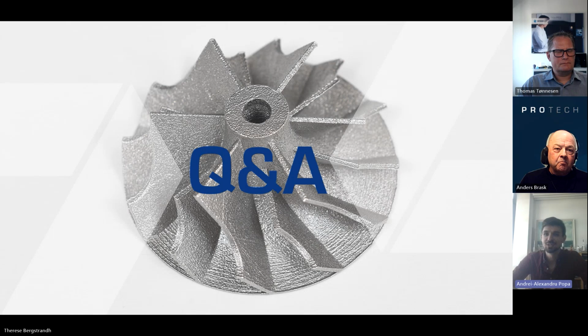Oh no, if you return to this large copper part we made, it consistently had bulges. There were bulges that did not prevent the printing from succeeding in the end, but that's exactly because of the soft recoating. So we could tolerate a little bit more in the geometry. So it's more fault tolerant in that sense. The design with a soft recoater is more tolerant, which means you have a higher chance of actually getting a part out of your print rather than a crash. Absolutely. And it can mean that the print is maybe not ideal, but I would rather take a part which is 99% dense instead of 99.1% dense, and it still works. I mean, it still exists.